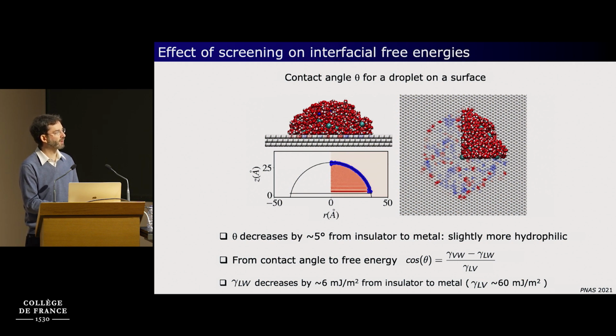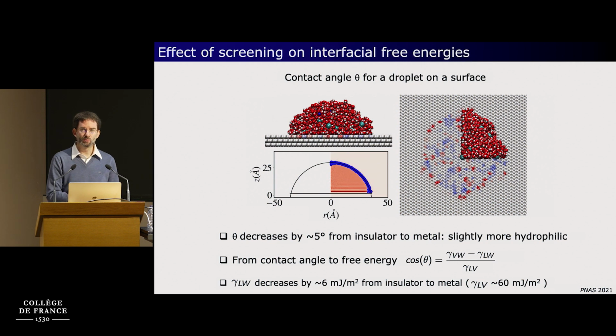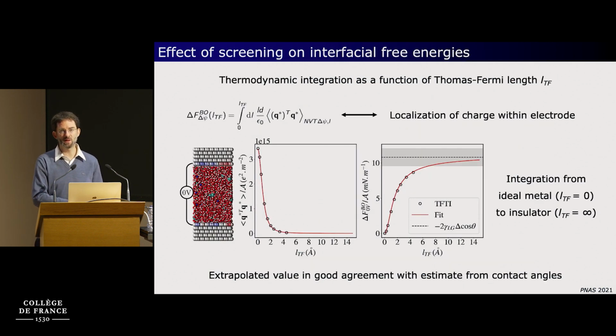And what you can compare it with is the interfacial tension at the water-air interface, which is a very high surface tension. And so this decrease is about a tenth of this number, which is considered as a very high interfacial tension. So it is significant. In order to compute the free energy in molecular simulations, it's quite expensive, and you have to resort to special tricks. And what we propose is a new thermodynamic integration method to compute this free energy change as a function of the Thomas Fermi length.